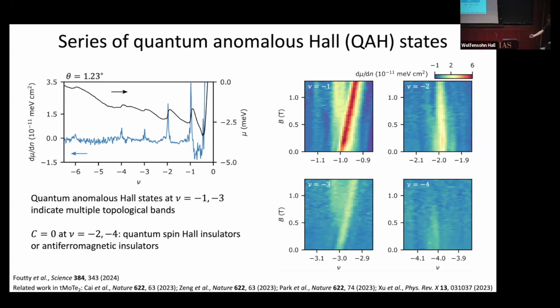So we have topological states at half filling. That is, we've presumably spin valley polarized the system as a result of interactions, and this gives rise to quantum anomalous Hall physics. The situation at these even fillings is a little bit unclear. It could be that this is a quantum spin Hall insulator. That is, you've occupied both of the Moiré bands, and one of them is Chern 1, one of them is Chern -1. That would give a net Chern number of 0, but there is a competing antiferromagnetic insulating state. So there are some transport reports that indicate probably this is a quantum spin Hall insulator, but we can't distinguish that from our measurements so far.